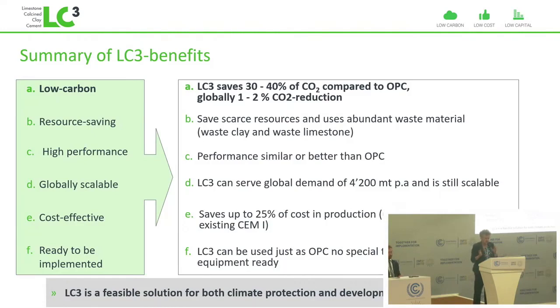So this is how we're tackling reduction of CO2 in the cement and concrete business, but this has to come together with the kind of measures we've heard about in previous presentations of reducing demand. And we can reduce demand without really any compromise, because it's been well demonstrated that most buildings today are over-designed and typically contain 30% more concrete than they need. So we haven't even got to change any codes, we've just got to make sure that people stick to the limitations that are already well established.